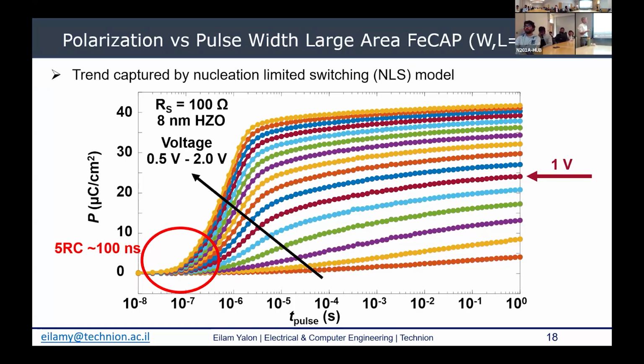What I'm showing here are our measurements for a large area device, a 100 micron by 100 micron capacitor. One of the things that we're interested in is looking at the high-speed operation. In this case, we're limited by the RC of this ferroelectric capacitor. So whatever we have below about 100 nanoseconds is not the intrinsic polarization switching speed. It's more parasitic.